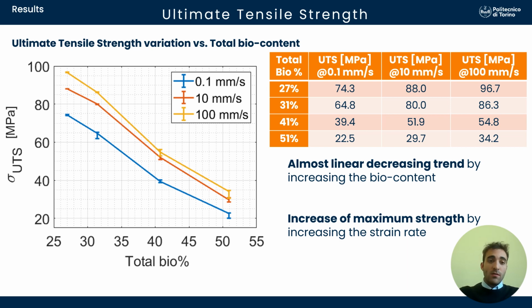Whereas here I reported the values for the ultimate tensile strength, considering also in this case 4 different materials and the 3 different strain rates. And also in this case we have an almost linear decreasing trend by increasing the total bio content and an increase of maximum strength by increasing the strain rate.